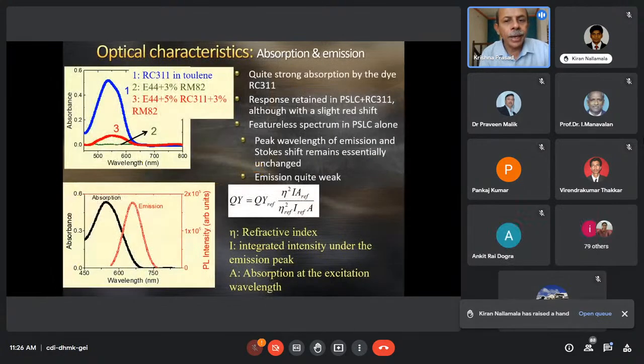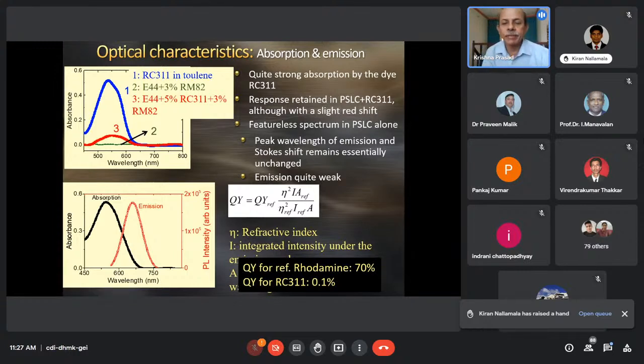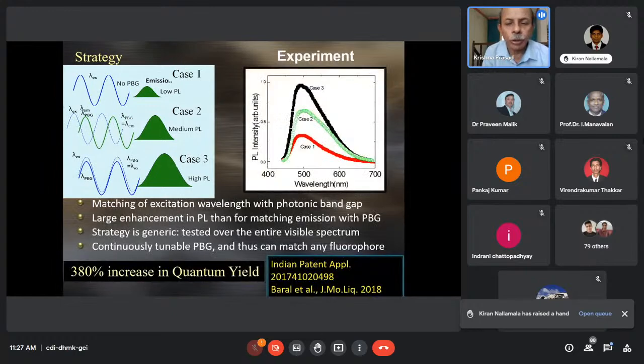I won't get into the details again, and I'll now come to the photonic properties, or the absorption and emission properties of such systems. The only thing that we need to remember is that we deliberately chose a very weak emitter for the system, and we saw that the system strongly absorbs, but its quantum efficiency is very low. The quantum efficiency is defined using an expression that is shown here, wherein there is a reference quantum efficiency material, and eta is the refractive index of the two materials, the standard and that of the parent system that we have. I is the integrated intensity under the emission peak, and A represents the absorption of the two kinds of materials. For reference, we chose rhodamine, which has a quantum efficiency of something like 70%. Compared to that, the emissive material that we have put in here has a very low quantum efficiency of 0.1%.